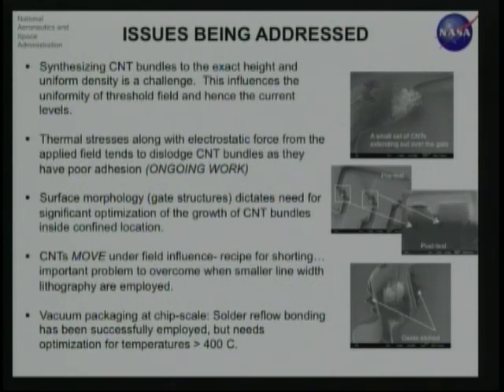There are lots of issues to be addressed in terms of how well you grow these tubes. Tubes tend to grow, so you should have a very good, well optimized process to keep the growth confined to a small location. Otherwise they grow tall and can short with neighboring electrodes. You could also have dislodging of the CNT bundles if you're not careful with your applied field. And there's significant morphology forming because of the gate formation on the silicon structure, so in a multi-layer process it's difficult to keep the line widths well defined.